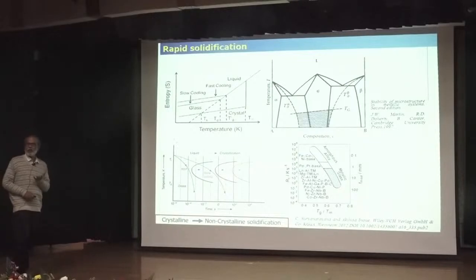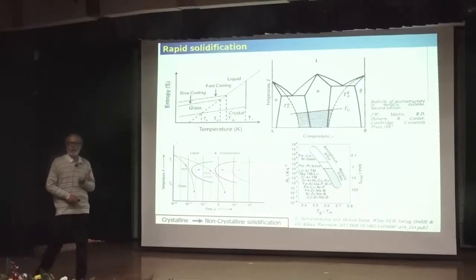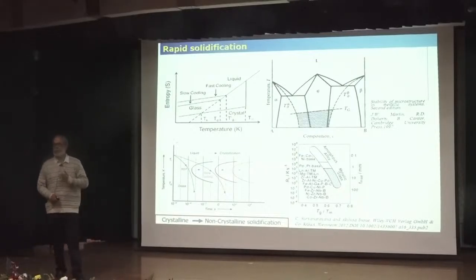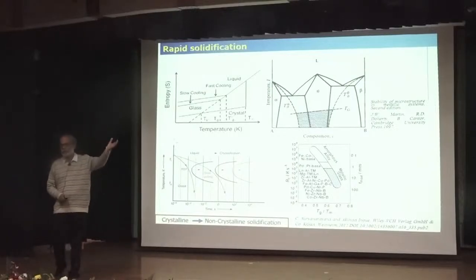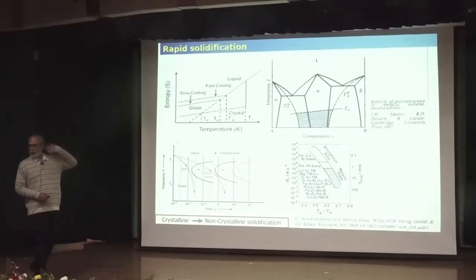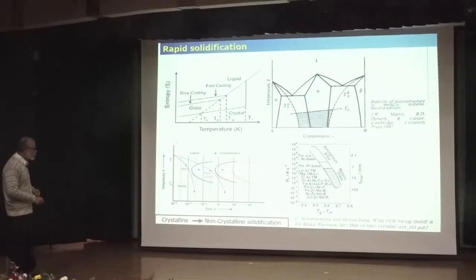So now one can produce glass with a cooling rate of 10 to the power 2 K per second in comparison to 10 to the power 6 K per second, what Pol Duwez did. And these are the alloys, the family of alloys where you have solidification to metallic glass.